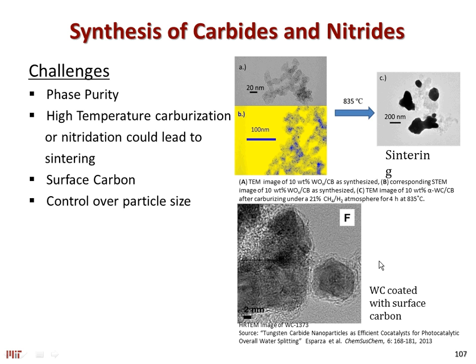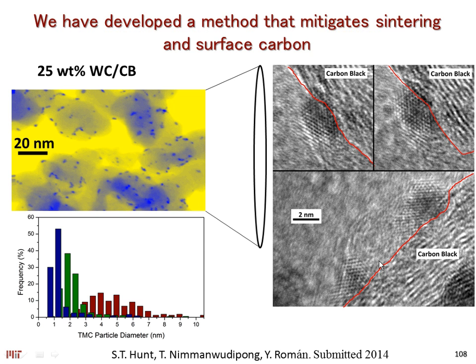And so we started looking a little bit more into carbides, which is a very interesting area of research, but synthesizing carbides is actually quite difficult, and it depends on the metal that you choose to carburize. For instance, tungsten is difficult to carburize because of the high barriers that you would have in putting the carbon in the lattice. You have this graphitic carbon that would go on the surface. And we recently developed this very neat technique to make very monodispersed tungsten carbide nanoparticles that have excellent activity for this HDO chemistry. I won't have time to show you some of these results, but what we find is very interesting structure sensitivity effects when you go to these very small sizes, when you do not have any carbon deposition, you have metal termination, and you have control over the phase and the composition of these carbides themselves.